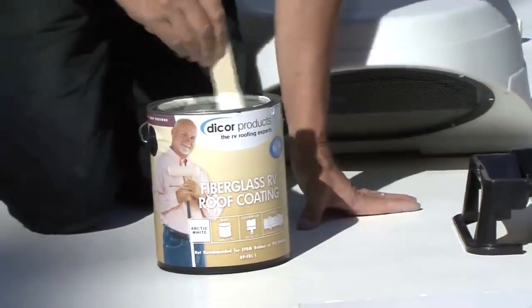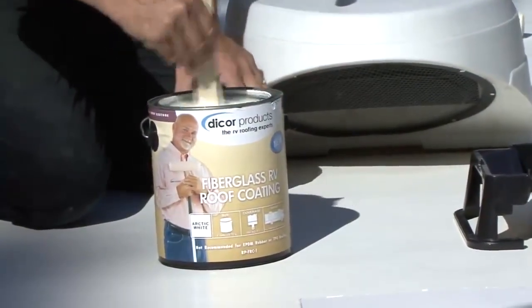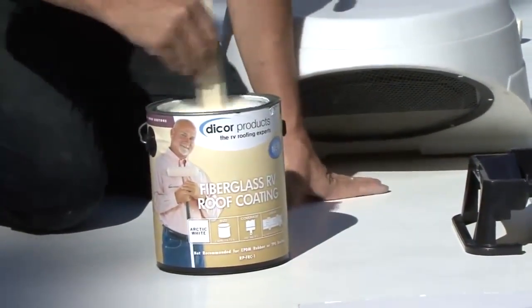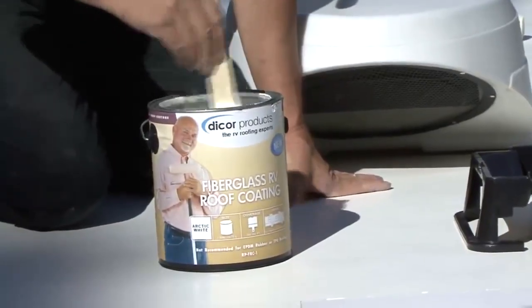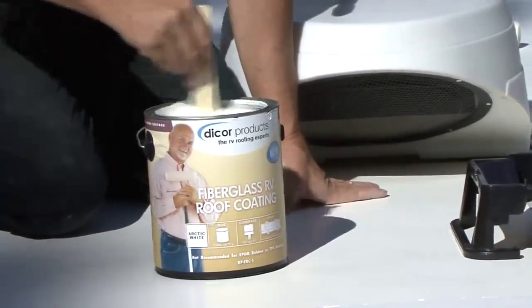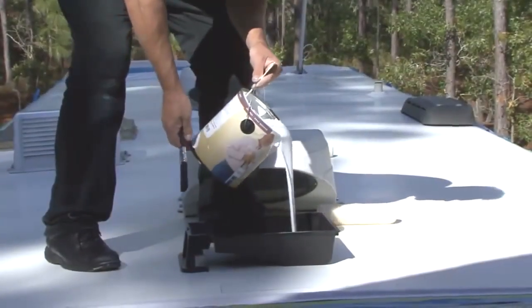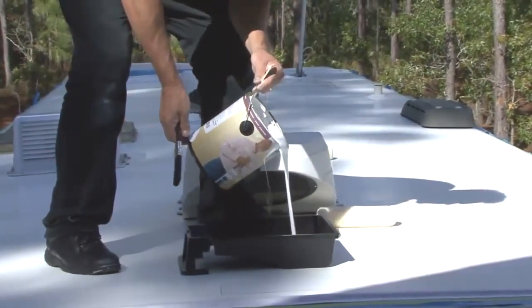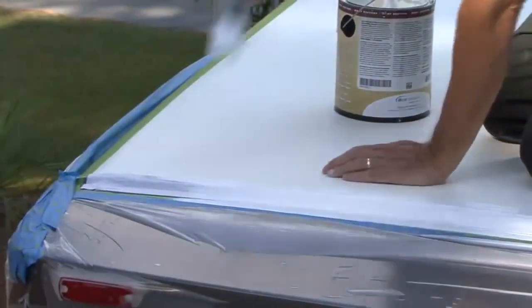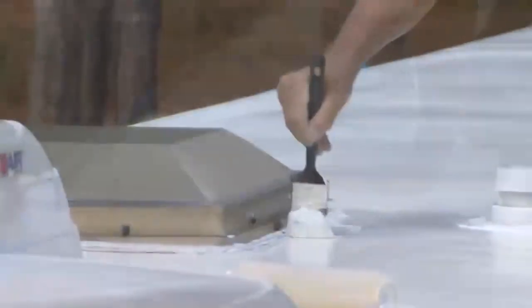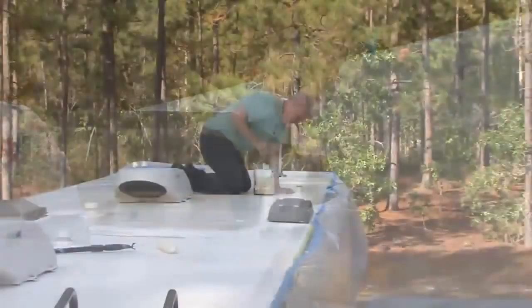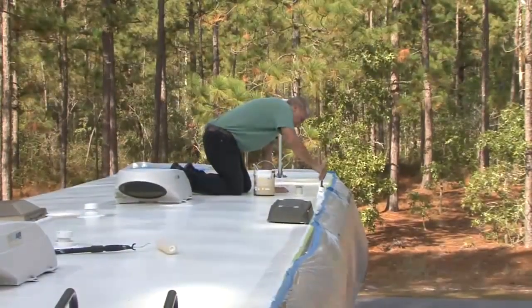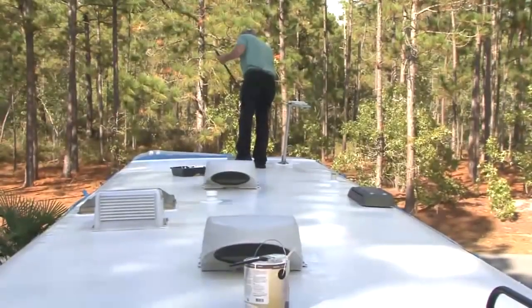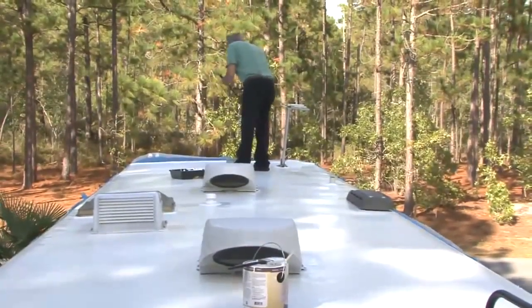Apply unthinned at the rate of 350 square feet per gallon per coat. Thoroughly mix the contents for a minimum of 5 minutes prior to application. For maximum performance, 2 coats are required. I prefer to go around all the edges and fixtures on the roof using a brush followed by a medium nap roller with a long handle. Apply each coat at right angles to each other by brush or roller.